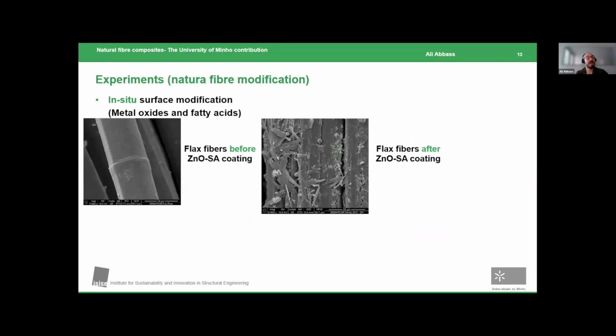So here you would see the same analysis of these fibers before and after coating. Before, you would see this neat, very pristine surface of the fibers, and afterwards you would see this robust micro roughness induced by microspikes, micro roses, micro lamellas. I don't know if I could use a mouse here. Could you see the? Yes. Okay, so here you have the micro roses based on the zinc derivative that has been grown onto the fibers.